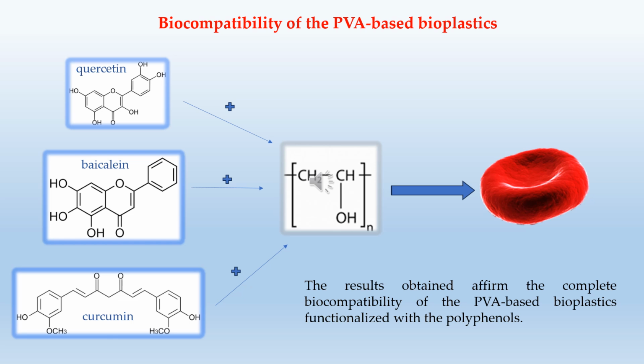Analyzing the data, it also emerges that among the newly created polymeric materials, although PVA alone is able to reduce the levels of hemolysis and methemoglobin compared to control, the ones with quercetin and baicalein incorporated into PVA showed the best results. Therefore, from the results obtained so far, we can affirm the complete biocompatibility of the PVA-based bioplastics functionalized with the polyphenol.